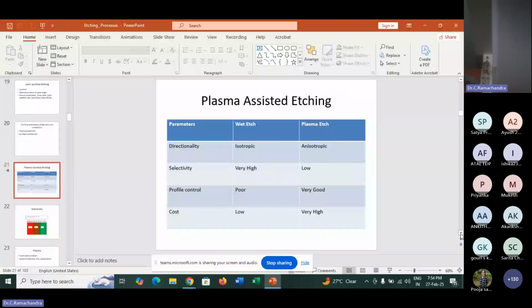So compared to wet etch, that means chemical etch, and plasma etch, these are all the advantages. Directionality: when we use wet etch chemicals, it etches in all directions. Most of the time I want to etch only in the vertical direction in device fabrication. That is a requirement. That means I want to have 90 degrees, but it is not possible in wet etch. It goes 45 degrees. Whereas it is possible to control the direction to some extent at least in plasma etch by choosing proper process parameters.